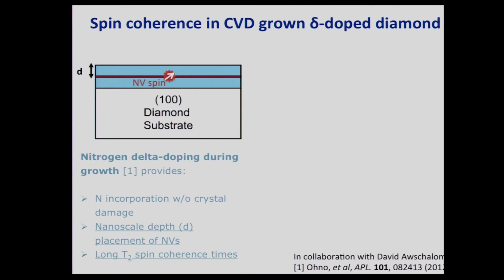Some other advantages of the system is that we can actually introduce nitrogen during the growth. So we grow the diamond, and then we introduce the nitrogen in a very thin layer where we can really control the depth below the surface down to nanometers. And in this way, we're introducing the nitrogen without crystal damage. The way that almost everybody does it is they implant nitrogens with a high-energy ion implanter. That's very damaging because in the process of ions bombarding the diamond, they create lots of vacancies and damage. This is a much gentler technique, and it also really allows us to position these in depth with nanoscale positioning, and it gives long spin coherence times. Here's some data that we, together with David, have published on the coherence times of NV centers that are right near the surface. So at a depth of 5 nanometers, we have coherence times of about 200 microseconds at room temperature, which is quite long.